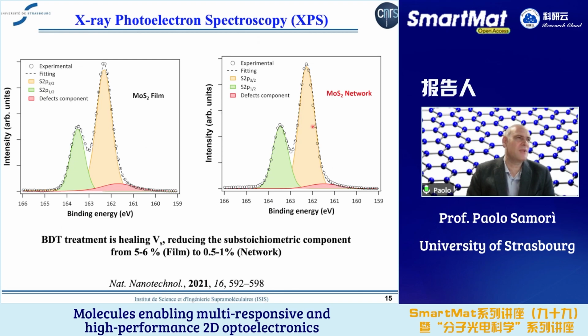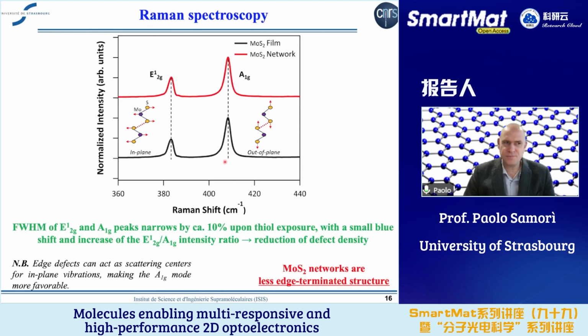The first characterization we did was X-ray photoelectron spectroscopy. On the left, I will put the film of disconnected MoS2 flakes, and on the right, the network. That is where the flakes are covalently connected. What you can see by focusing on the S2p peak of the XPS spectra is the substoichiometric component, this defective component, which if we pass from the film to the network, decreased drastically from 5% to 0.5%. So we have decreased the number of defects.